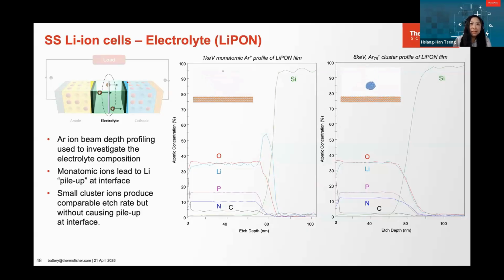So here is an example showing depth profiling of a proposed electrolyte for solid-state batteries, which is lithium phosphorus oxynitride. On the left-hand side is the monatomic profile. You can see there's a very sudden increase in the lithium concentration just at the interface.